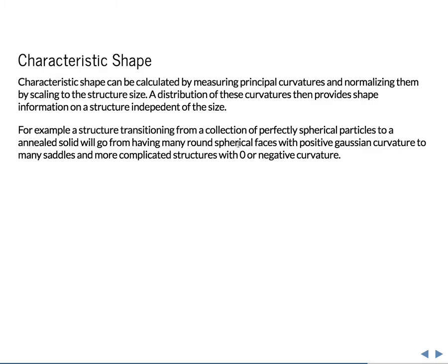And if you're looking at very small objects, you get a very poor representation of what that actually looks like. If you just have 1 pixel-sized objects, you'll end up with everything being perfectly spherical, even though in reality they probably are not. A lot of times you'll see studies showing that objects become more spherical as they get smaller, when in fact this is really an artifact of the fact that if you only have 1 pixel, all you can be is perfectly spherical.